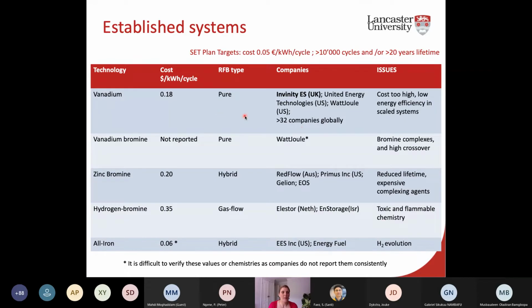But generally, there's usually a boom and a bust with vanadium flow battery systems, where they get a big investment and then they seem to go bust shortly after. So there's a lot of trying to retain and keep that market going and show that they are competitive with lithium ion batteries. And then you've got companies looking at zinc bromine, lots of different zinc systems out there, but zinc bromine being the most successful. You can see the cost is actually not yet competitive with the vanadium system. Despite zinc and bromine in themselves being low cost, the complexing agents for zinc bromine make it much more expensive.